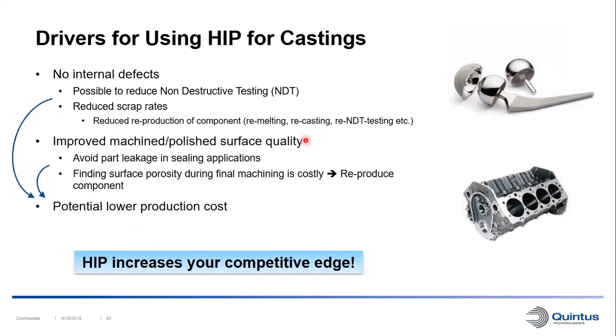More outcomes. So very common in the casting industry is of course to use non-destructive testing such as X-ray analysis to make sure that the internal porosity is within allowable limits. But since we're eliminating this porosity with the HIP process, it might be possible to reduce the non-destructive testing or even eliminate that part of the process chain. And this will of course save cost.